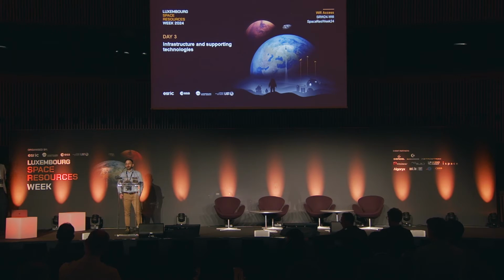Regarding the first question, so far the only thermal cycle we tested was a limited one, going between plus 60 and minus 60 Celsius. We will increase the cycling in the near future, so I don't have a proper answer. It works at plus or minus 60, it isn't becoming brittle. What I can tell you is that the PEEK itself would work at low temperatures. It might become a bit fragile at very low temperatures, but the behavior of the composite material is still something that we have to see.